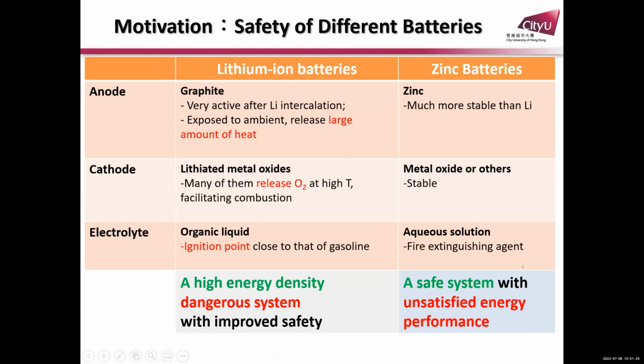If you compare lithium batteries with zinc batteries, in terms of the material systems, graphite is stable, but if you intercalate lithium ions into graphite, it will be very active. The cathode is lithium metal oxide. Sometimes it can release oxygen at slightly high temperature, which can facilitate combustion. On the other hand, the electrolyte is organic, which has an ignition point close to that of gasoline. So lithium batteries are generally a very high energy system, but very dangerous. Intrinsically, in terms of materials, it is very dangerous.